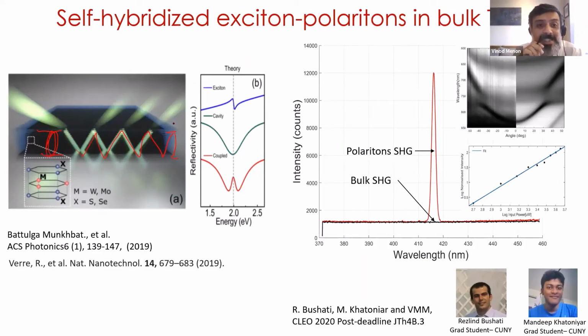And what you will see is that once you look at the system, because there are excitons in this system, if I couple those excitons to this mode that gets trapped inside, I can get the typical Rabi splitting property. So what we did was we made such a system. We made a bulk material. So it's just a bulk material.